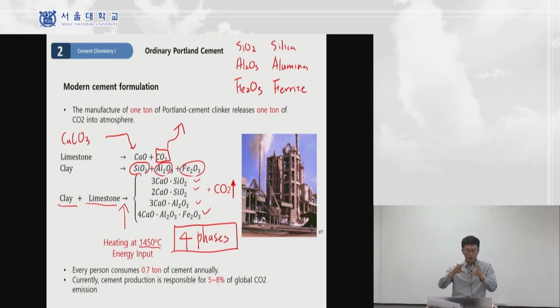They are all decomposed at this very high temperature, and they have a chemical reaction between these two. It will produce CaO, SiO2 when they bind together: 3CaO·SiO2, 2CaO·SiO2, 3CaO·Al2O3, and 4CaO·Al2O3·Fe2O3. So you will see these 4 phases. These are the main components in the OPC. Ordinary Portland cement is not a single material. This is a mixture of these 4 phases.